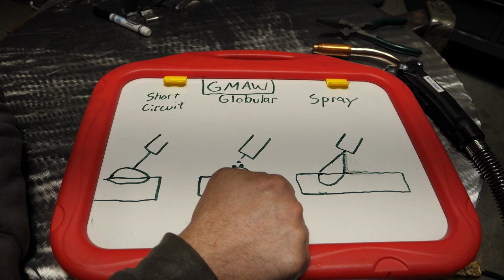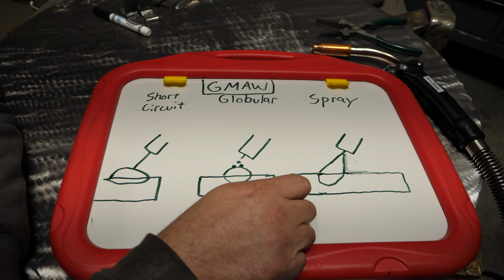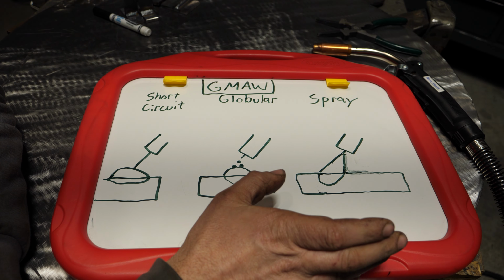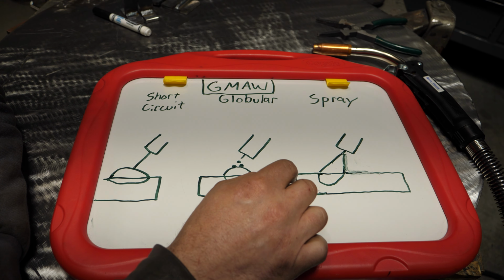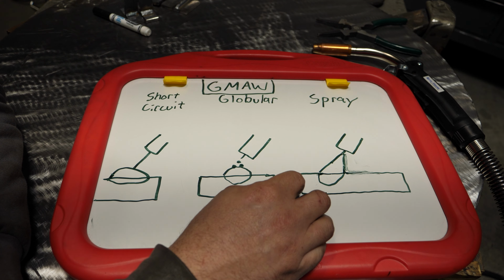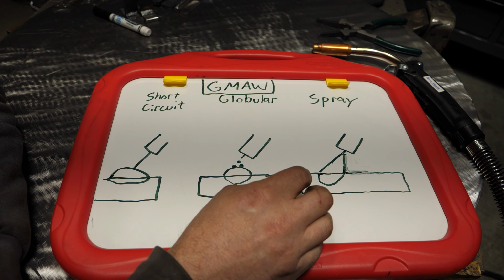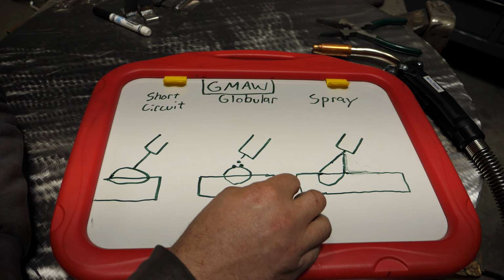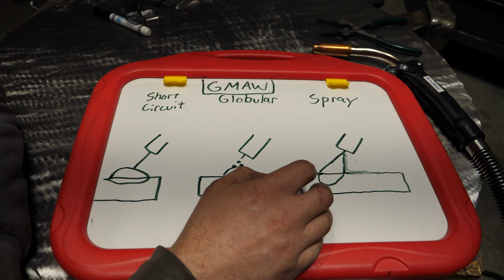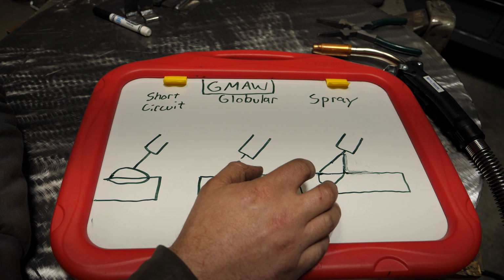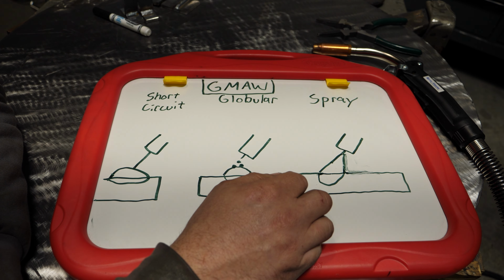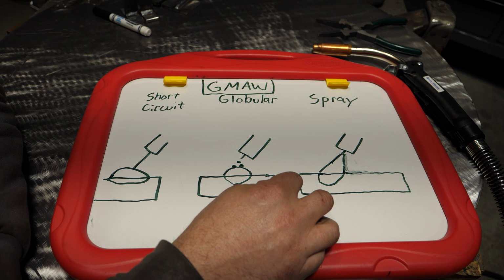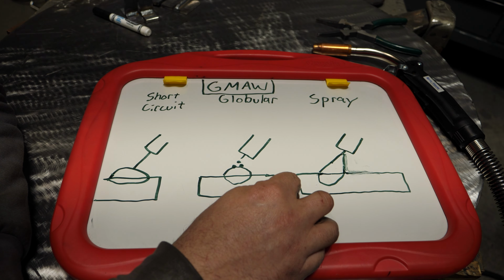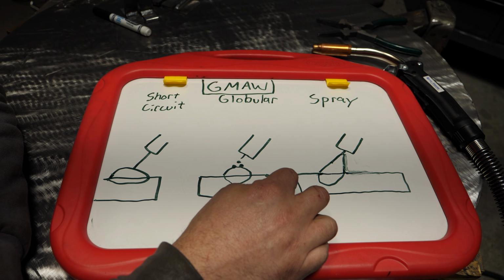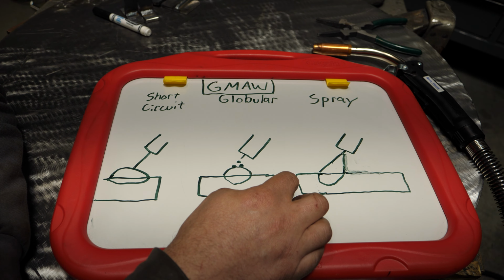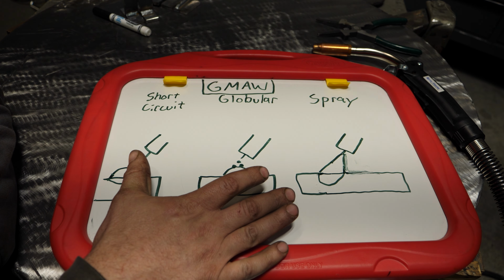When you switch to spray, even though you're using the same welder, the same wire, provided your welder's capable of it, with just a change in shielding gas and much higher values, you can now safely get root fusion, get penetration, and weld thicker plate. And that's where the main benefit comes from with spray. So it's performance, it's deposition, and it's speed. And it's fairly affordable, provided you have a welder that'll run it. So I think you understand this a little bit better.